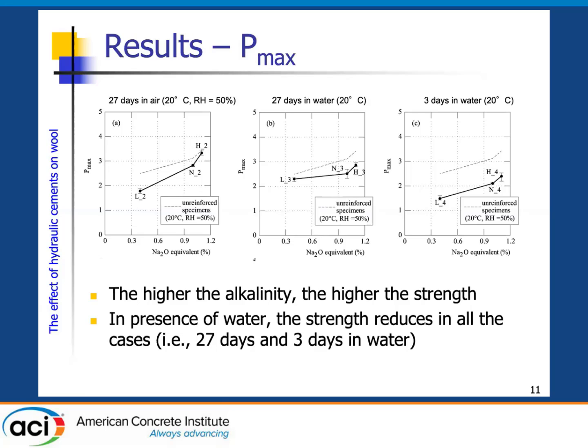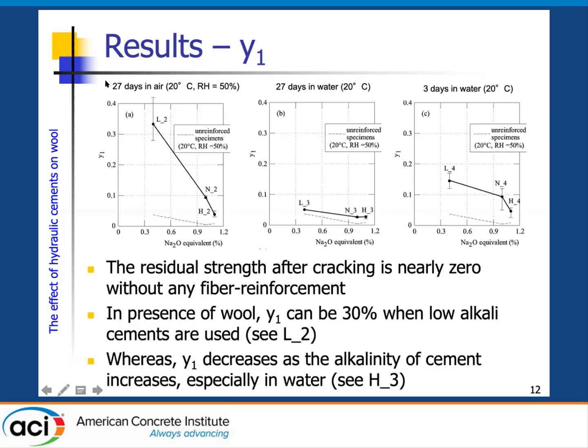In our case, we would like to see the capability of fibers, so we have to observe what happened after the cracking, so in the post-peak diagram, and in particular on Y1. Y1 is more or less the percentage of residual stress with respect to the strength of the material. As you can see, as the content of alkali increases, you have a reduction of the residual stress in all the specimens, and from 30% of L2 we move to 0.05